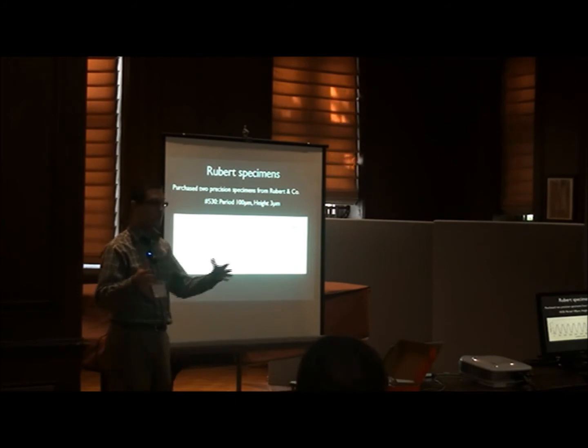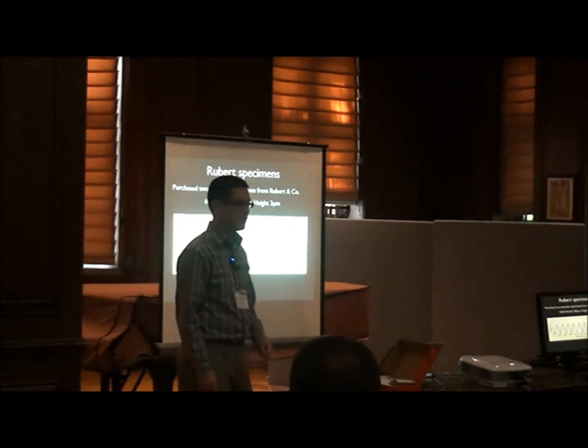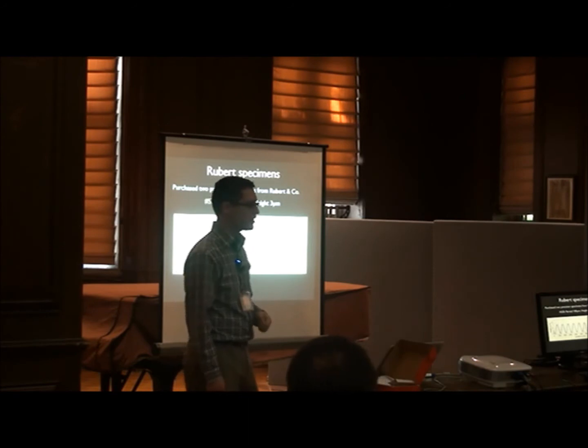So what I plotted here is our measured surface, and this is a scan line out of the center of the image. We in fact measure, of course, the whole surface. And I took a scan line out, and then in the red dash curve is an analytic sinusoid plotted with the same parameters that the manufacturer said. But it's not an independent profilometer, it's not an independent... No. It is just a sinusoid. That's right, it's a pure sinusoid.